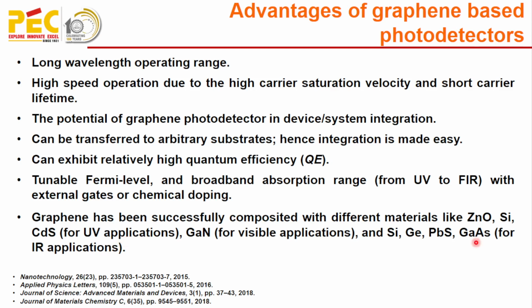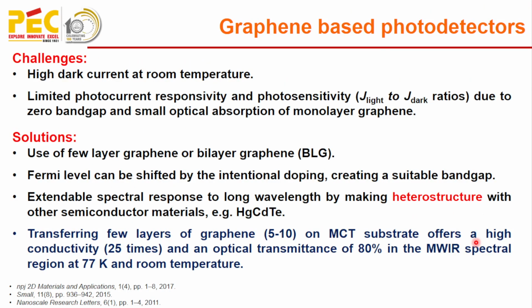Now we have some challenges for graphene-based photodetectors. Due to the zero band gap and small optical absorption of around 2.3% in the case of monolayer graphene, the graphene-based photodetector will suffer from high dark current at room temperature. They have limited photocurrent responsivity and photosensitivity. To avoid this, we can use few layer graphene or bilayer graphene, and we can tune the Fermi level by intentional doping, which will create a suitable band gap, and the spectral range of graphene can be extended by making a heterostructure with other semiconductor materials such as mercury cadmium telluride.